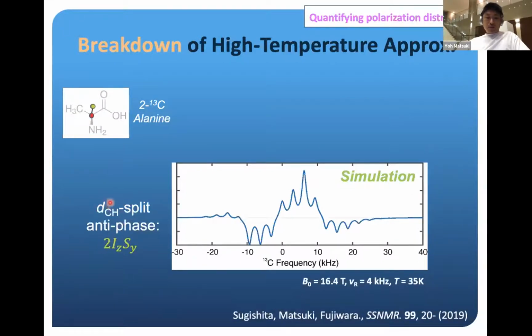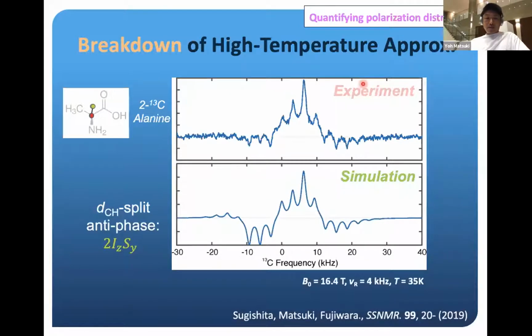Right, this cross term for a proton-carbon two-spin system will look like a dipolar split, antiphase, powder pattern, convoluted with the spinning side bands like this. And in experiment, we got this. This very good agreement indicates that already at 35 Kelvin, the high temperature approximation is visibly violated. And the spin correlated term is big enough and readily observable in experiment.